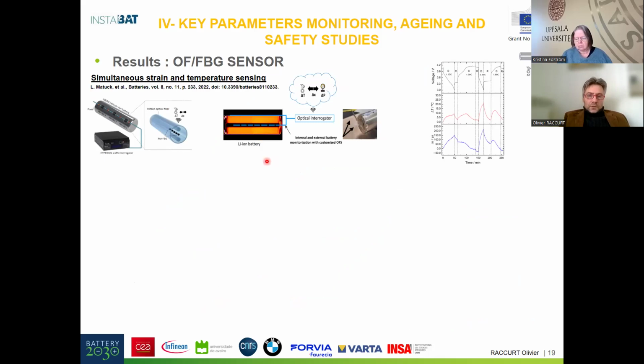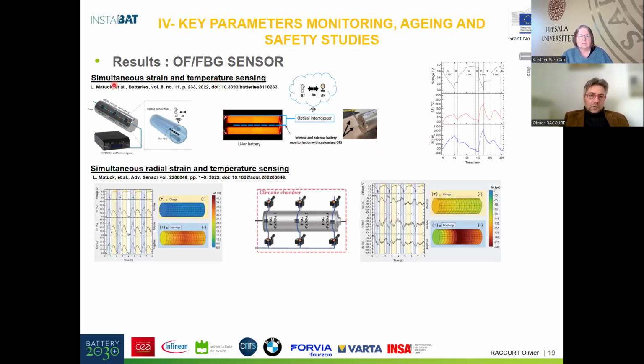Now I give you a first result. It's not on the pouch cell, but on a commercial cylindrical cell. We put the hybrid sensor, Panda fibers with FBG, to monitor the temperature and the strain related to the pressure. We compared the results inside the cell and outside the cell, and we validated that the sensors are able to monitor at the same time the variation of temperature and the variation of delta epsilon inside the cell. You can see the results in this publication for each part. I give you the reference of the publication.